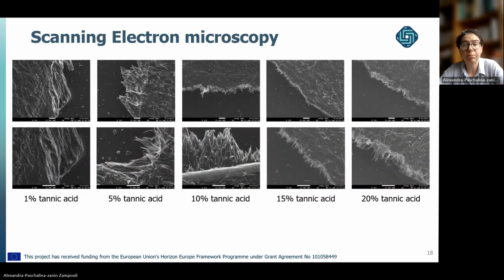And here we have some photographs from scanning electron microscopy of the fracture surfaces of the composites. And we can see that with low tannic acid content, we have longer fibrils on the fracture surface. When the tannic acid content increases over 15%, the fibrils are much shorter, indicating a brittle material.